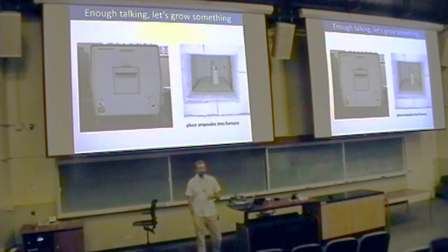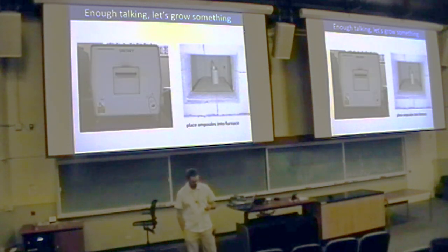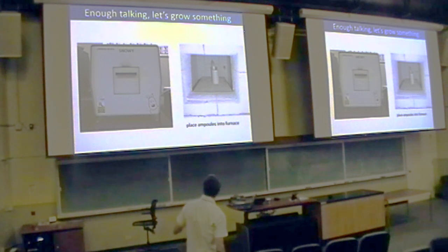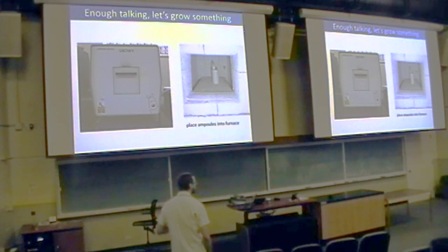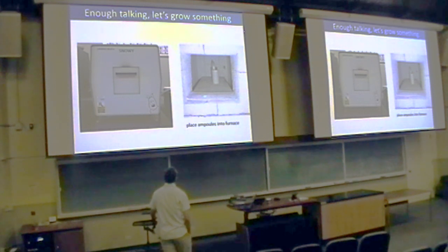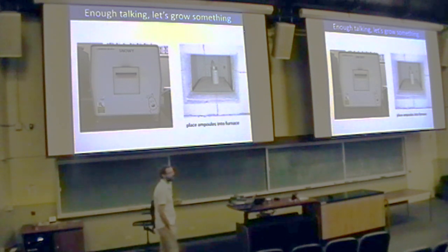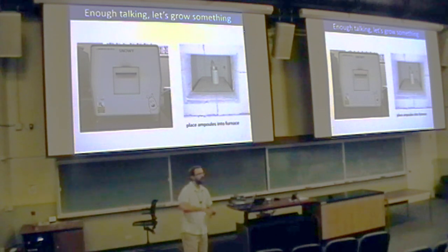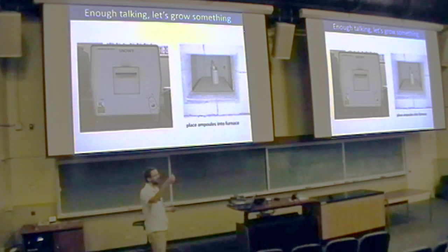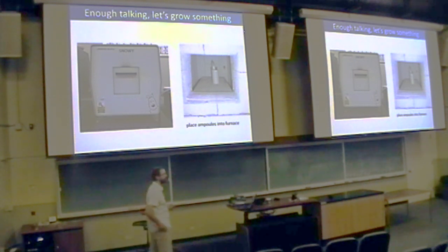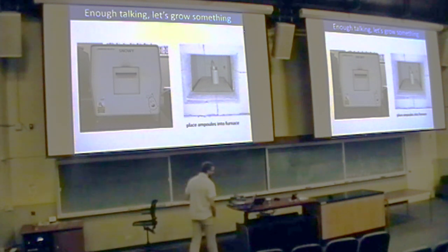Then we're going to put this into a furnace. In my lab, all the furnaces have a name. So this one is Snowy. And we're going to leave the ampule sitting in another crucible so that it stands upright. We leave it in the furnace, and we warm up to get a liquid region, and we slow cool so that we grow the crystals slowly in the furnace.